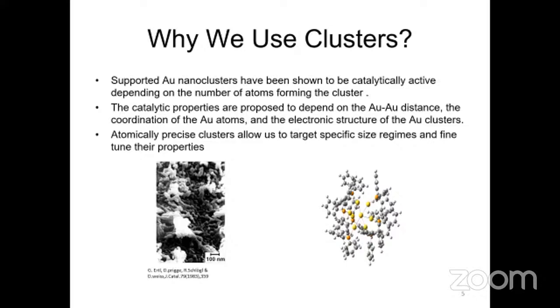To have this cluster as stable as we can, we have to protect it with ligands. These ligands around the cluster are for stabilizing the gold core. But once we need to do the catalytic reaction, we need to remove the ligands to have the core of the gold naked for the catalytic reaction. We need to study the geometry and the structure, because every catalytic activity is different depending on the size, geometry, structure, as well as the electronic structure. That's why it becomes different by counting the atoms of the nanocluster itself. And we need to tune the size regime to understand their properties and catalytic activities.